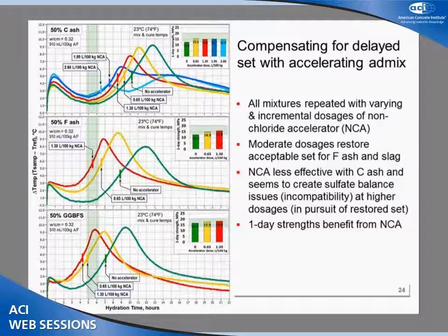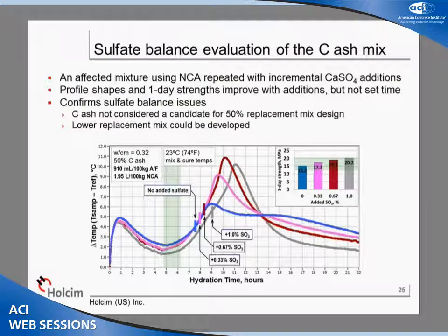And to confirm this, if you're interested in doing this, it's very simple: just reproduce one of those mixtures with incrementally higher doses of a separate calcium sulfate addition. This can be ground source gypsum, laboratory grade Terra Alba gypsum, or even plaster of Paris from your local hardware store. And sure enough, as you increase the SO3 level of the resulting mixture, we restore normal shapes. We show much improved one-day strengths, confirming that we had an incompatibility sulfate balance problem.